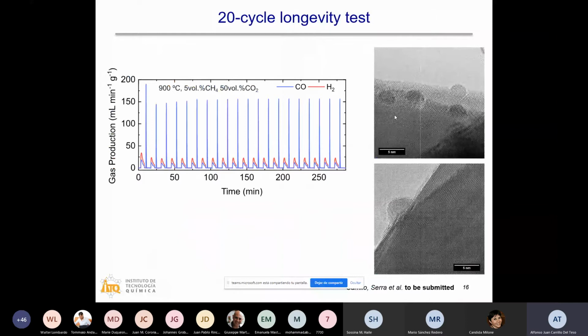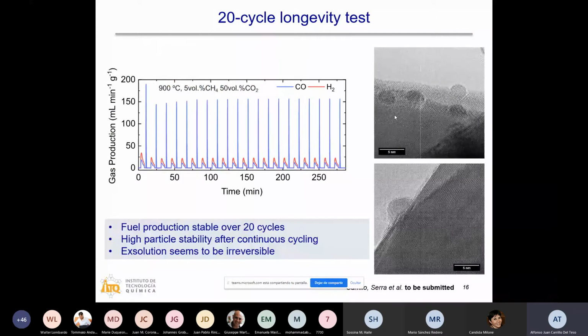We check, obviously, the durability of these materials and of the process as well. And here, for this experiment, I increased the amount of CO2 in the CO2 splitting reaction. Increasing the CO2 partial pressure will also increase the gas production rate for the CO2 splitting. We observed that this is very stable. And we also checked by TEM the materials after these 20 cycles at 900 degrees Celsius, and we observed that the ruthenium nanoparticles are still there, attached.